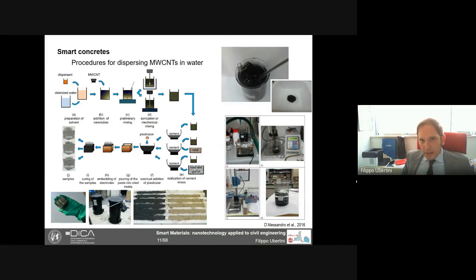One big difficulty in dispersing nanotubes in concrete is that we need to disperse the nanotubes in water first, and then add cement and aggregate and so forth. And to disperse the nanotubes in water, we need a lot of attention, and typically we need sonication and sometimes magnetic stirring. This, of course, is not suitable for large-scale production. So one way we proposed in the work by D'Alessandro and co-authors, referenced in the bottom right of this slide, to get rid of sonication was to use dispersants that are chemical surfactants that change the surface of the nanotubes and improve the possibility to disperse them.